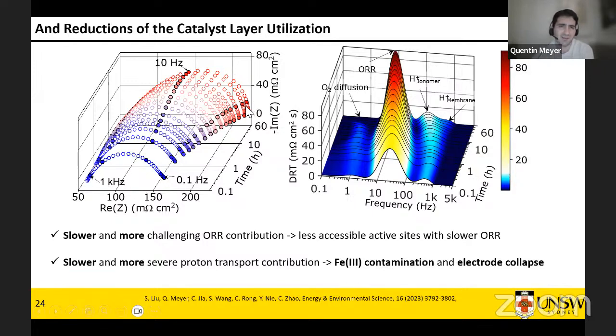What's likely is that maybe carbon corrosion is happening, and gas diffusion limitation is happening at much, much lower frequencies. But because the system was not very stable, it was difficult to do a very long measurement. Like this measurement lasts 3 minutes. If we wanted to look at much, much lower frequencies, we may need to measure for 1 hour, which was not possible given the rate of decay. But this is the picture we obtained.